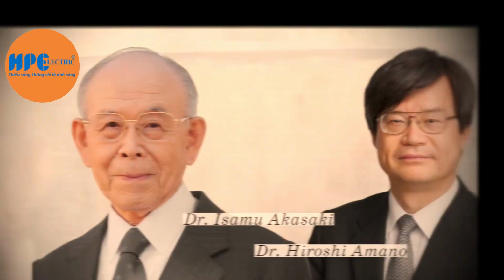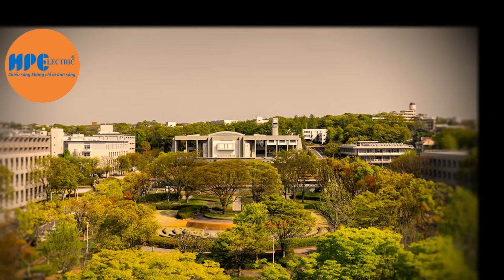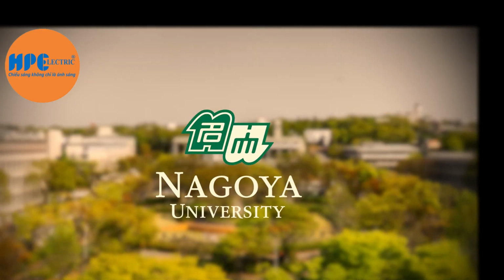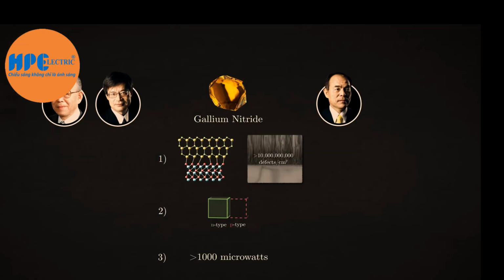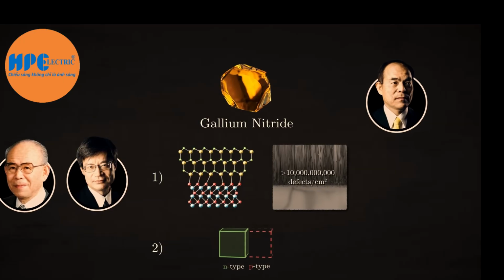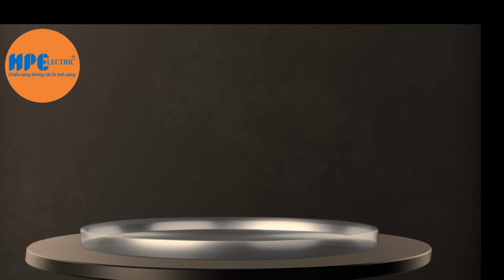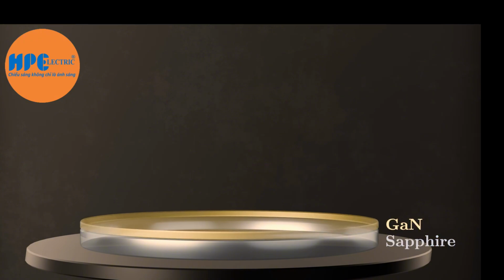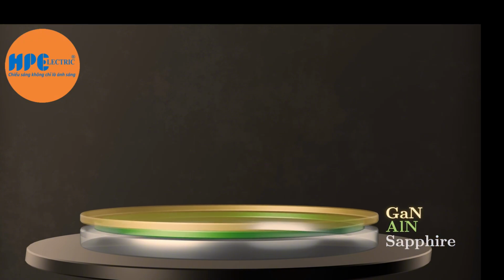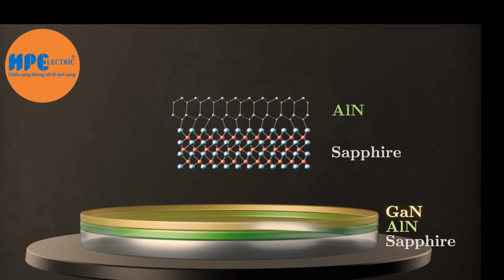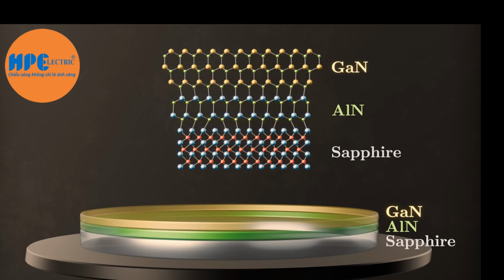2 of those 5 attendees were the world experts on gallium nitride, Dr. Isamu Akasaki and his former grad student, Dr. Hiroshi Amano. In contrast to Nakamura's academic background, they were researchers at Nagoya University, one of Japan's best. A few years earlier, they had made a breakthrough on the first problem of high-quality crystal. Instead of growing gallium nitride directly on sapphire, they first grew a buffer layer of aluminum nitride. This has a lattice spacing in between that of the other two materials, making it easier to grow a clean gallium nitride crystal on top. The only issue was that the aluminum caused problems for the MOCVD reactor, making the process hard to scale.